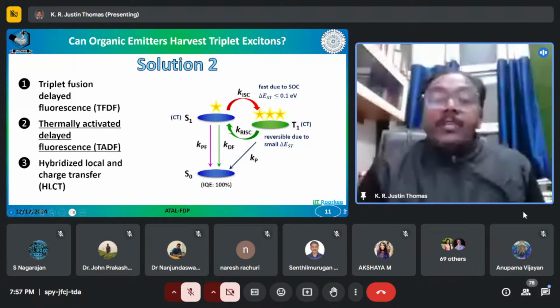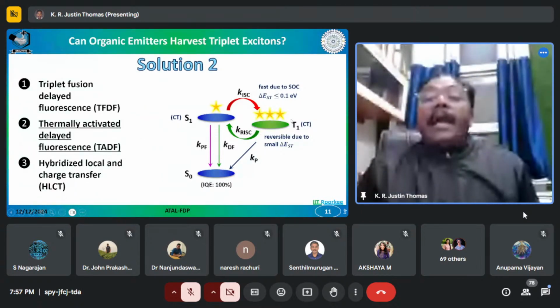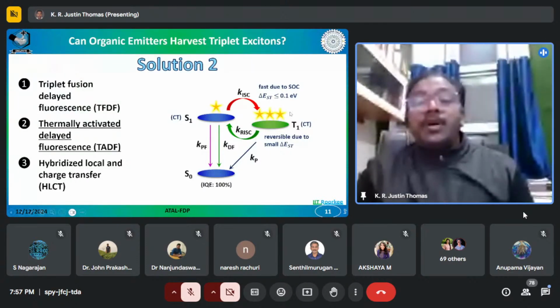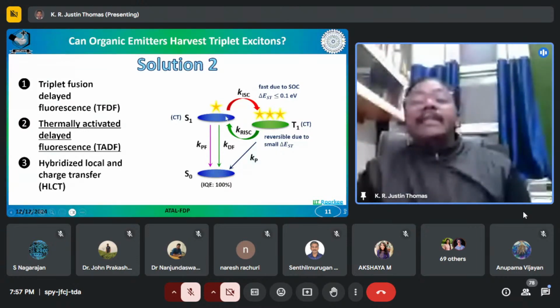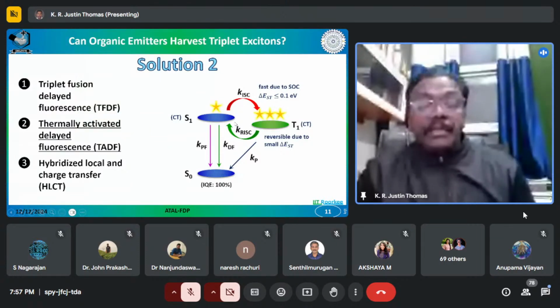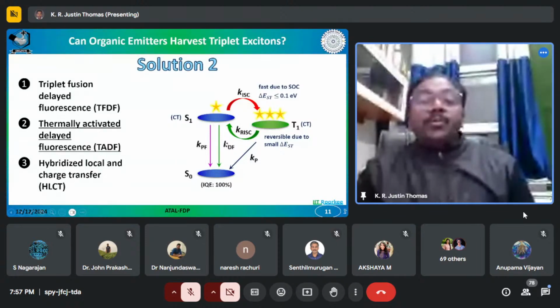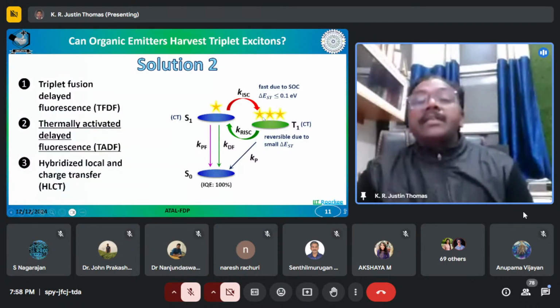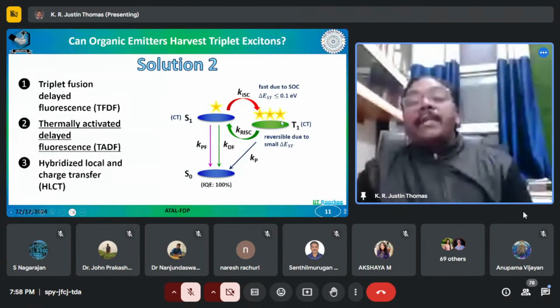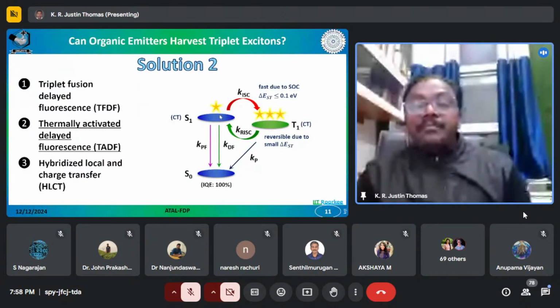In such molecules, it is found that the triplet excited states are closer to the singlet excited state, and the delta EST, that is the energy difference between the singlet and triplet excited states, is less than 0.1 electron volt. Since the energy separation is very small, this energy gap can be overcome by thermal energy. That is the reason it is called thermally activated or thermally assisted delayed fluorescence. Now, when you excite an organic molecule by shining light, it goes to the singlet excited state, and since the triplet excited state is close, thermal vibrational energy converts it to a triplet excited state by intersystem crossing. Again, it can come back to the singlet excited state by reverse intersystem crossing. And then finally, the emission takes place from a singlet excited state.